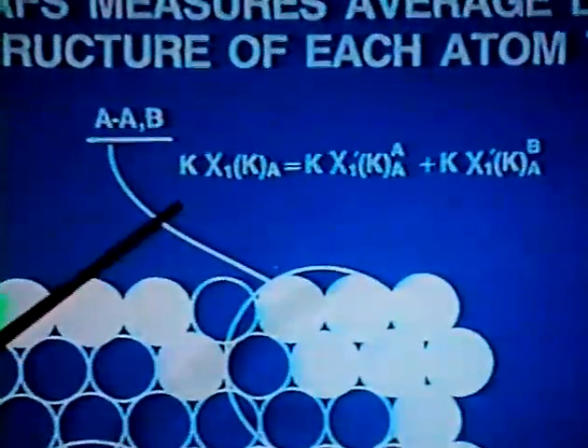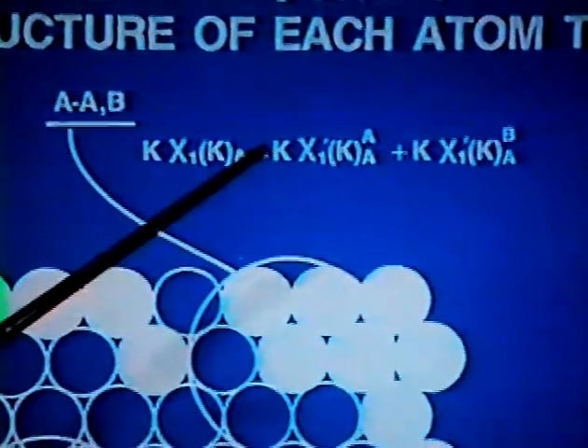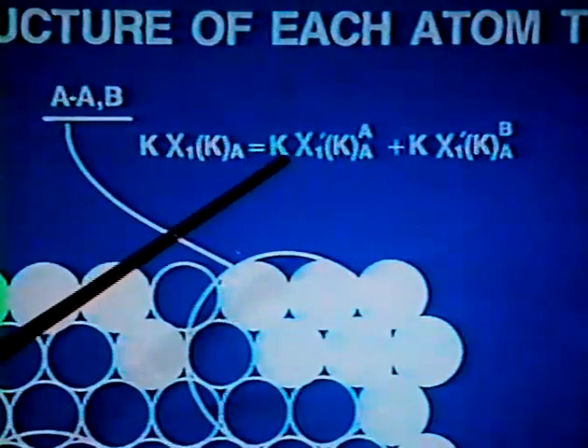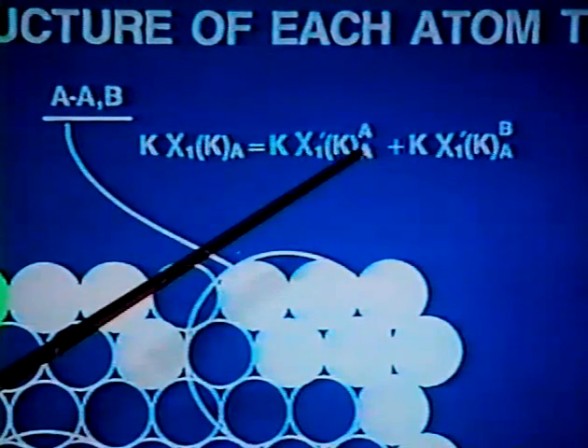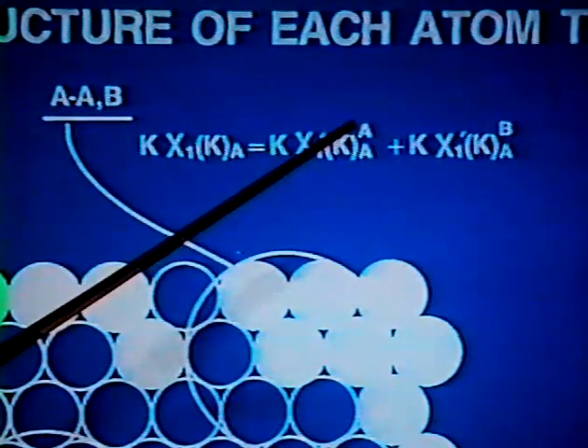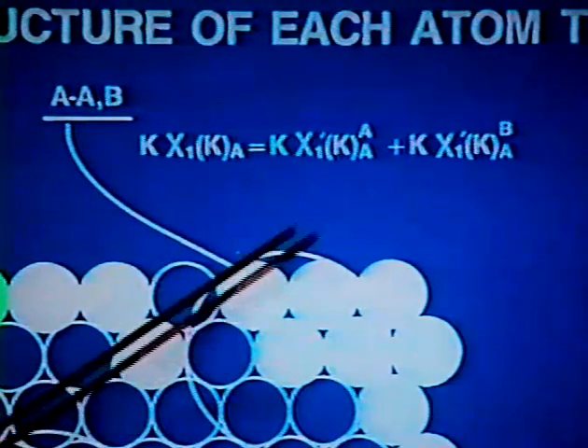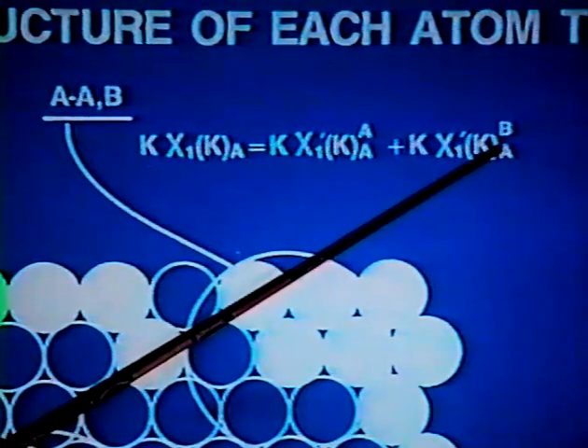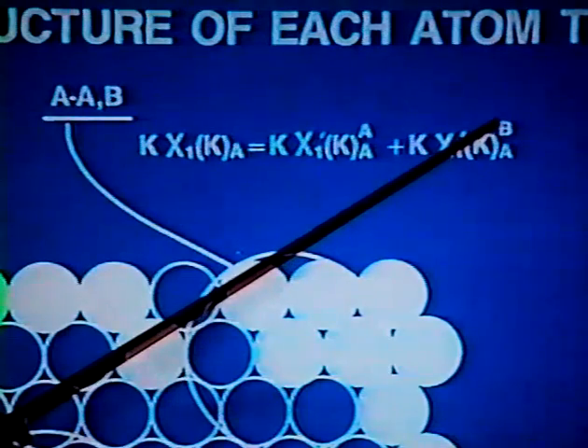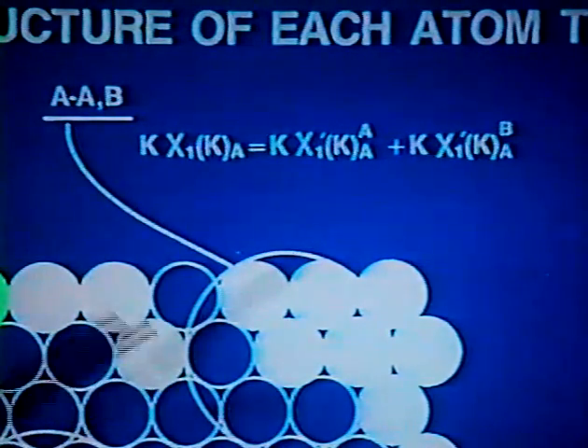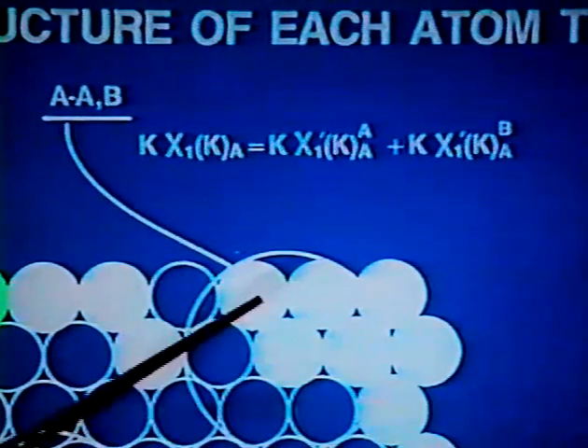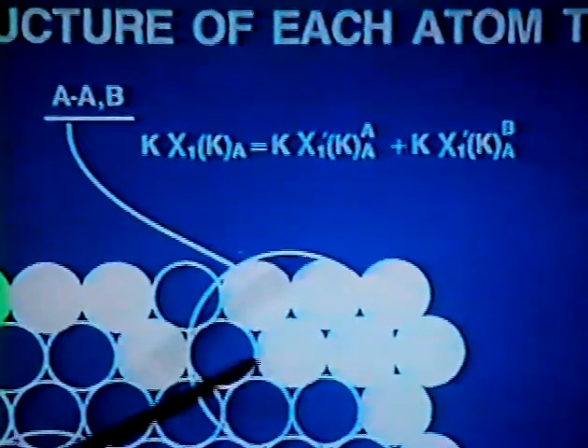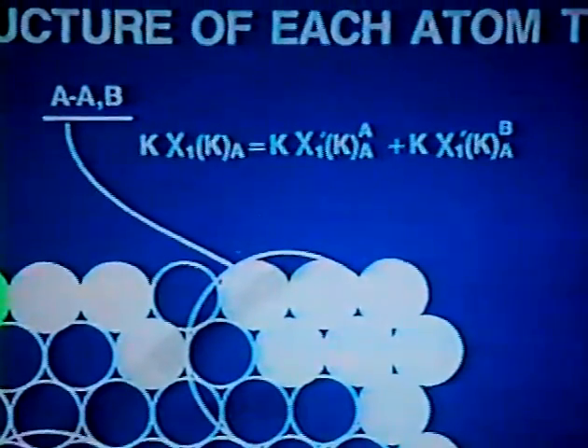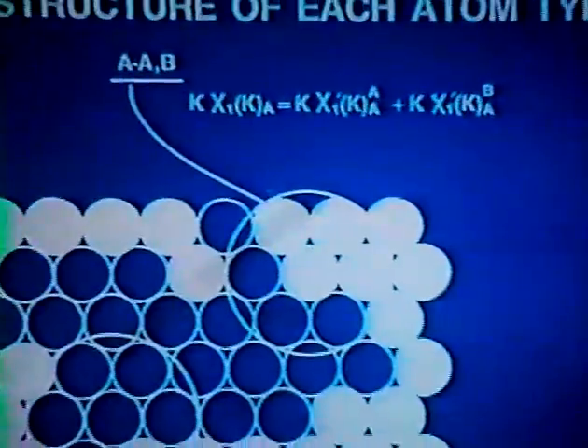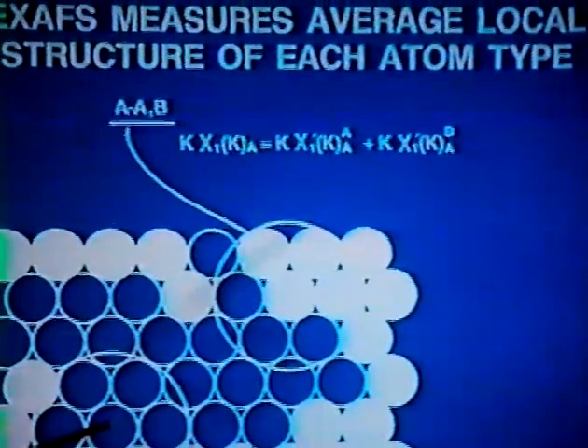Now, the EXAFS, given by this quantity here, from the white atoms is represented by a term due to absorption by the white atoms and scattering by the neighboring white atoms, and another term due to absorption by the white atoms and scattering by the black atoms. That is, we've got photoelectrons scattered by these atoms, and those different contributions add together to make the EXAFS.